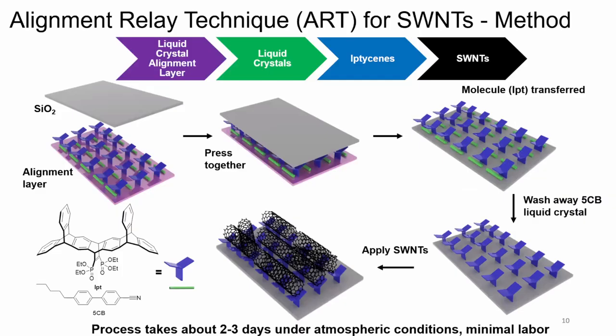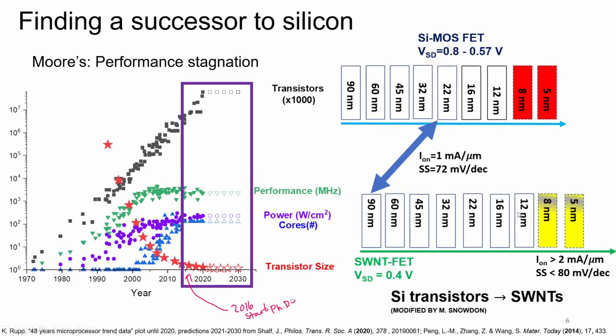Oh yeah. I'll go back to the slide. Silicon MOSFET. I don't think they're on here. In terms of on-off ratio and subthreshold slope, that's also a very important parameter that I didn't touch on. Basically, it's the slope of how fast you go to the on-off ratio. This is very good, but with carbon nanotubes, we can get higher. Yes, silicon is great, but with carbon nanotubes, even at the larger scale, we still have the same kind of properties as silicon. If we scale down with CNTs, we can get even better results.